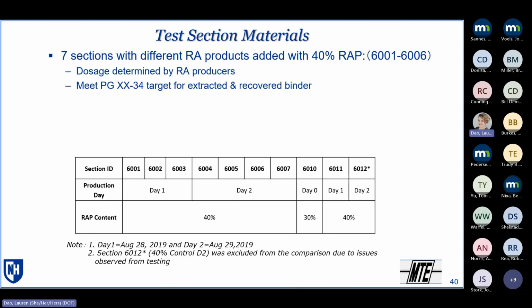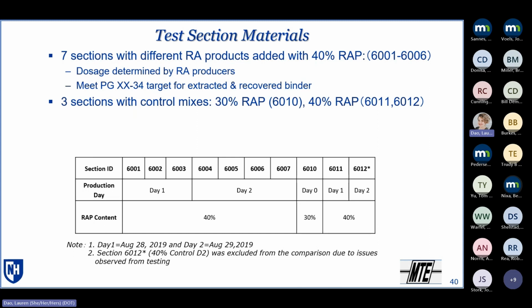So we've got the 7 test sections with the 7 different products, and then there were 3 control mixes. There's a 30% control mix, which is the typical material that is used on the rest of the project out there. And then 2 40% RAP sections for the 2 different days of production that didn't have any rejuvenators in them. So 2 different controls, the typical that would be used, and then the 40% to directly compare with those. And you can see the dates of the paving on those.